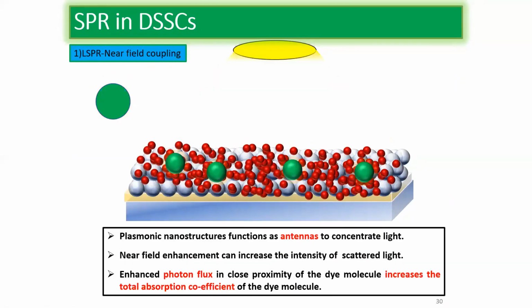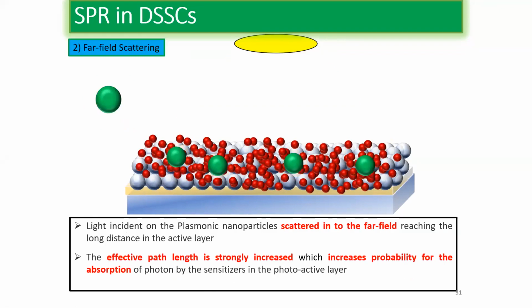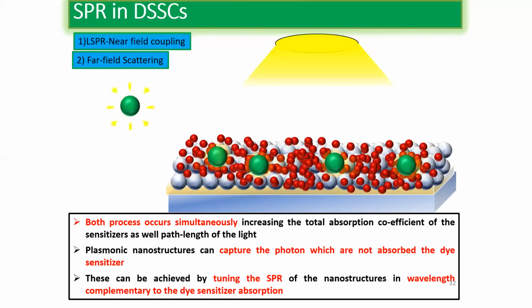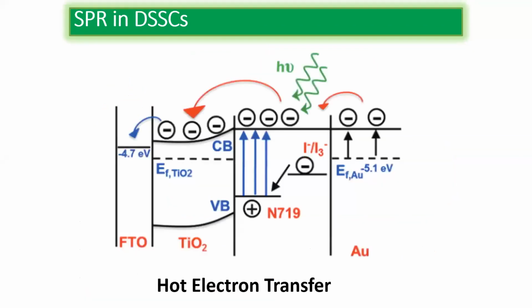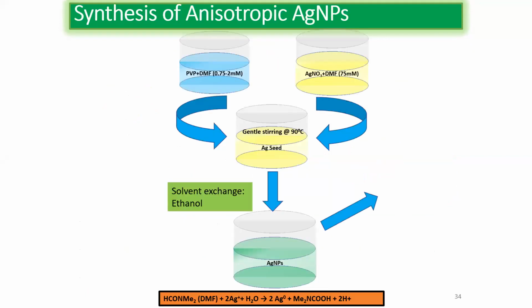So this is the LSPR effect, near field coupling. I told in my previous slide that there are two effects, near field coupling and far field scattering. This schematic shows how near field coupling works. And another is far field scattering. This is also very important, where the total optical length of the material increases. When the plasmonic nanoparticle gets excited with light, the emitted light goes into the long region. This is called far-field scattering. Generally both types of effect occur simultaneously. All nanoparticles, based on size, have some extent of both, as I have shown in that graph. So this is the way we can utilize this material. This is the material I have synthesized.